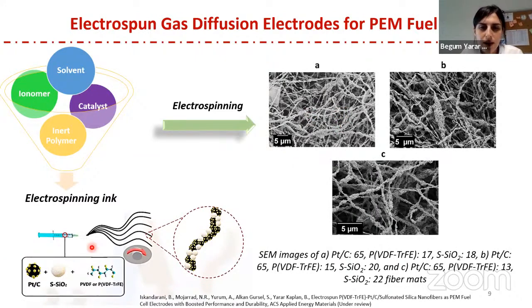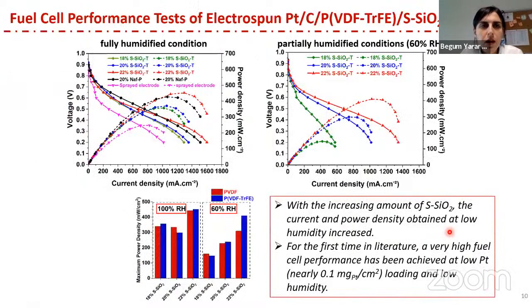You can see the schematic of the electrospinning setup also. As you can see here, we didn't use Nafion solution in the electrode structure. We use sulfonated silica to provide better water retention ability to the electrode, and we perform fuel cell tests at both fully humidified and partially humidified conditions. As you can see here, the electrodes show very promising fuel cell results using a very low amount of platinum, and the obtained power output is also promising at partially humidified conditions.